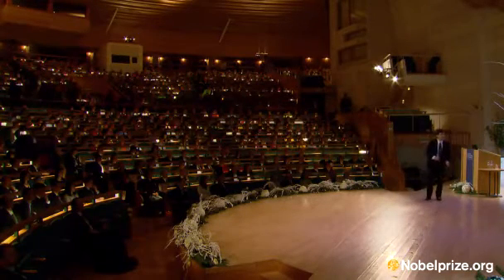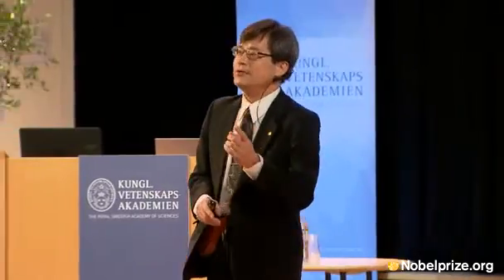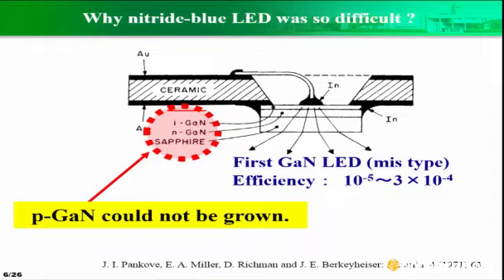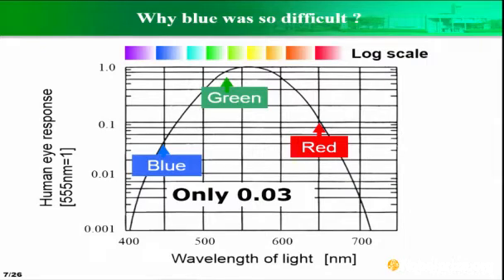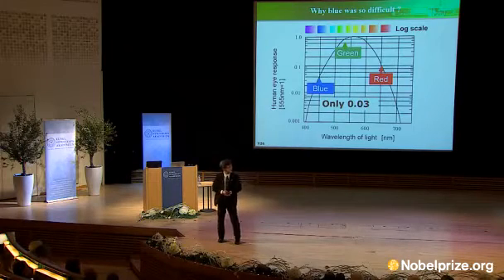Professor Pankove developed in 1971 the MIS-type gallium nitride using hydride vapor phase epitaxy, using metal gallium, hydrogen chloride, and ammonia. But they could not achieve p-type gallium nitride, so the efficiency was limited to be low. Also, another difficulty in achieving bright blue emission was related to the sensitivity of the human eye. The responsivity to pure blue light is only 3% compared with the yellowish green 555 nanometer emission light.